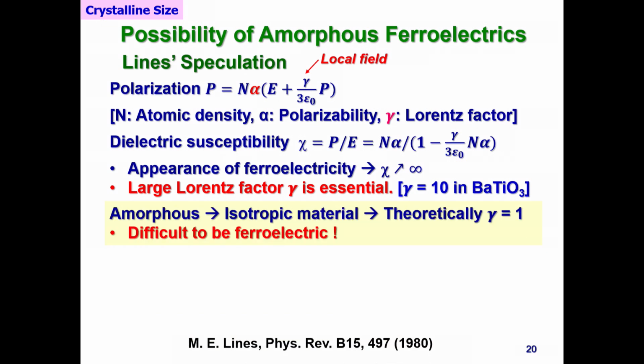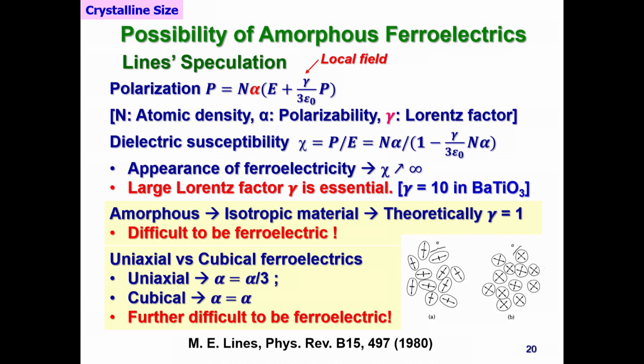However, for amorphous, unfortunately, even lead titanate, if we make it amorphous, theoretically gamma becomes 1. So it doesn't become any ferroelectricity, okay? And particularly if you take some uniaxial type dipole moment, it's totally impossible. And so amorphous ferroelectric research was boosting, but completely failed out in less than 10 years, okay? So after the 1990s, nobody is working with the amorphous ferroelectrics. So amorphous doesn't make any ferroelectricity.